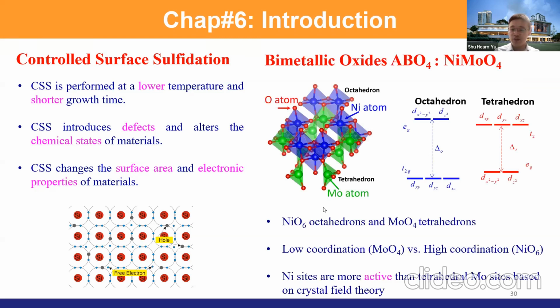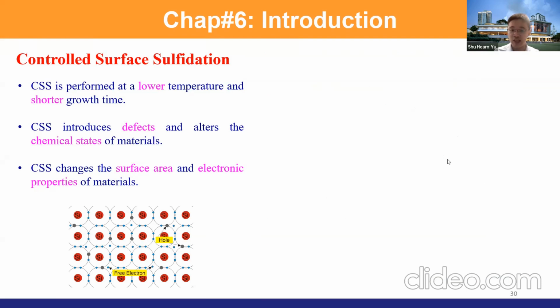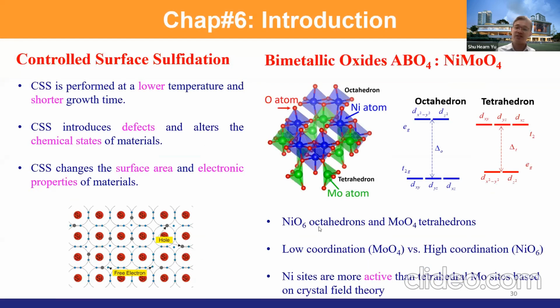So first of all, I would like to talk about the nickel molybdenum oxide. This is the first step. I grow nickel molybdenum oxide on the nickel foam, which is here. In nickel molybdenum oxide we have a nickel oxide octahedron and molybdenum oxide tetrahedron. This is the structure. If you know crystal field theory, then you know that nickel sites are more active.